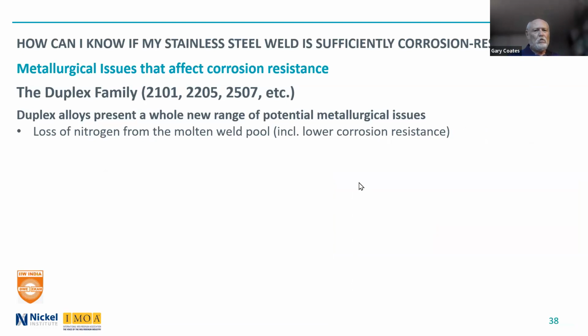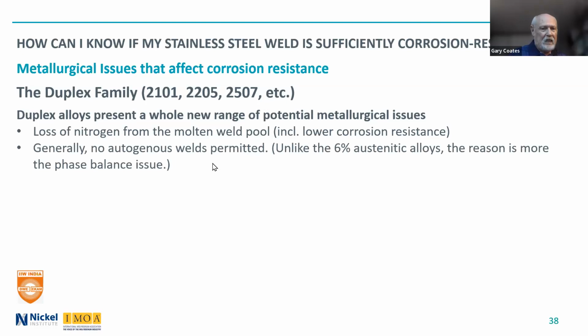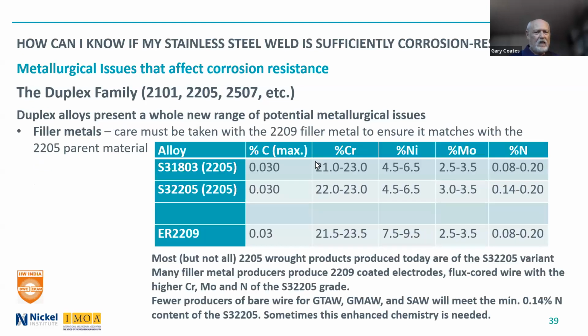So what is important in the welding? Well, loss of nitrogen from the molten welding pool. You have nitrogen in the base material, it goes into the molten state, and some nitrogen can come off, and that can result in lower corrosion resistance and a poor phase balance. Like the 6% moly alloys, we generally say no autogenous welds. There may be special circumstances, and unlike the 6% moly austenitic alloys, the reason is more the phase balance issue, not the intermetallic issue. There's a limited number of filler metals, and I'll come a bit more into that right now.